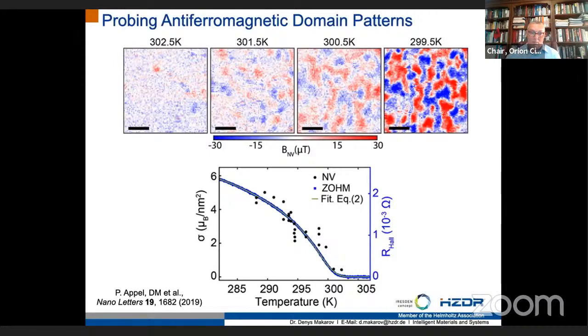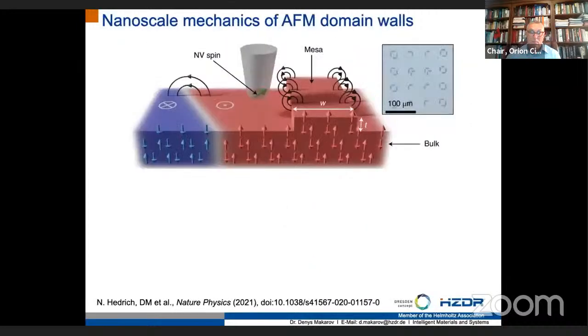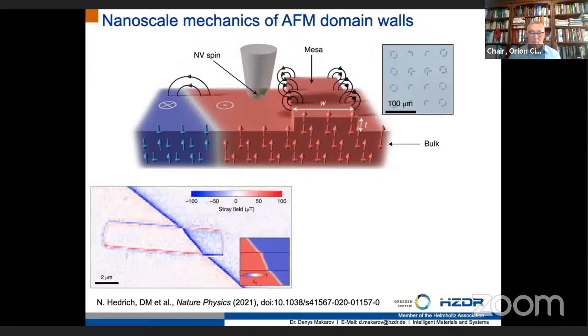In order to understand what is the impact of the presence of defects like grain boundaries on the pinning of magnetic domain walls, we went back to the analysis of the very well-defined system. It's a single crystalline chromia with a C-axis and the Z-axis pointing out of plane. The quality of this material is very good, meaning that antiferromagnetic domain walls were not stable in these samples. In order to stabilize the domain wall, we patterned the array of mesostructures, as it's shown here schematically, on the surface of the sample and performed magnetoelectric cooling of the materials through the Néel temperature to impose the presence of magnetic domain wall, which is now pinned on one of these mesostructures.